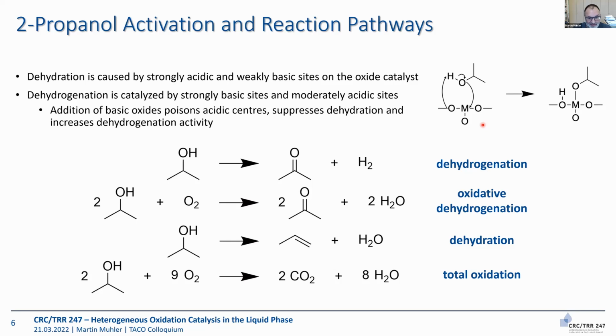Now, major question, why do we want to oxidize 2-propanol? From an industrial perspective, it's not attractive. That is something I have to admit. But from a fundamental point of view, it's an interesting molecule because it's well established in heterogeneous catalysis that with 2-propanol, you can both probe redox properties and acid-base properties. Redox properties, either the catalyst catalyzes just dehydrogenation to acetone and hydrogen, or in the presence of oxygen, it can catalyze oxidative dehydrogenation. And when you do so, then the coupled product is water.